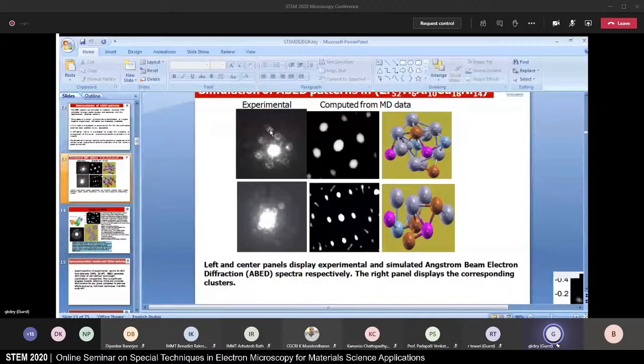Then we have this one. If you have a cluster you have already deciphered, now you want to examine the relationship of one cluster with the next cluster. So if you want to do that, you have to make the beam slightly larger so that you examine 2 clusters at the same time. And then you get a diffraction pattern, which is a superimposition of the diffraction patterns from the 2 clusters.